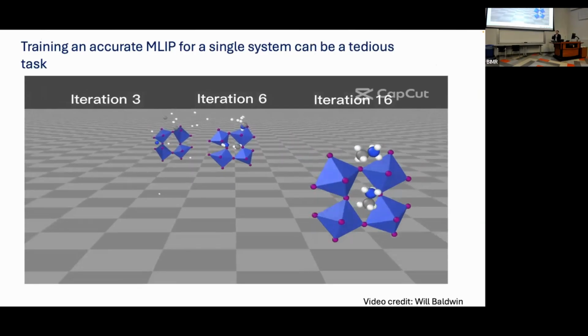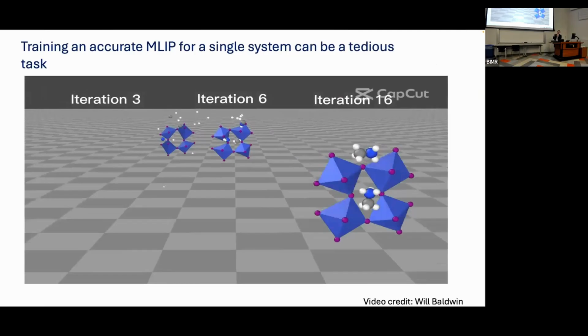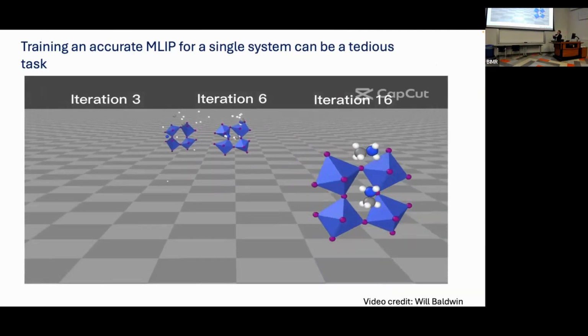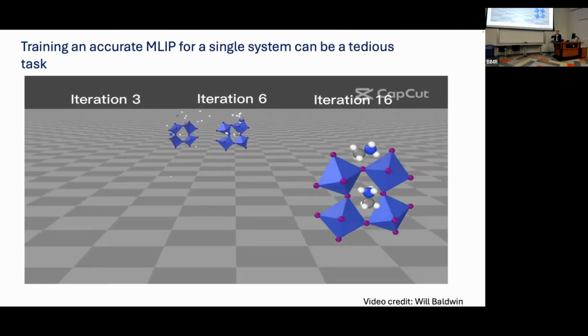And machine learning is just interpolating. So it hasn't seen it, it doesn't really know how to handle it. And in some cases, you'll see that the atoms get too close or they just totally break. And then eventually, you reach a point using active learning schemes where you run enough MD simulations and you find the cases where it's blown up, and you add that back to the training set and you retrain the model. Eventually, you get to a case where now you have a stable potential. And you can do great things with that, like I showed with the phase diagram, but it takes many, many loops to get to this point sometimes.